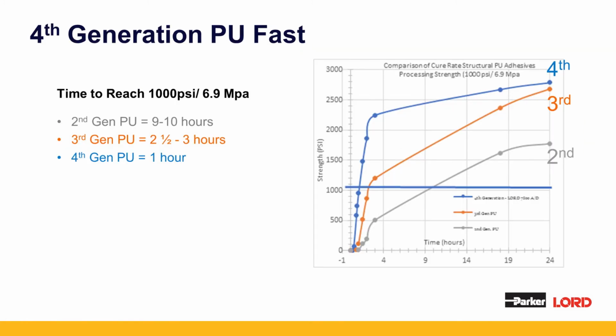So we can see here on this slide, talking about the processing strength in the 4th generation polyurethanes that Parker Lord has introduced. Graph on the right shows the strength development, and this has been measured via ASTM D1002, lap shear strength, on E-coated steel. You can see here that the 2nd generation urethane, 3rd generation, 4th generation are all represented, and all of them have a 3 to 7 minute open time.